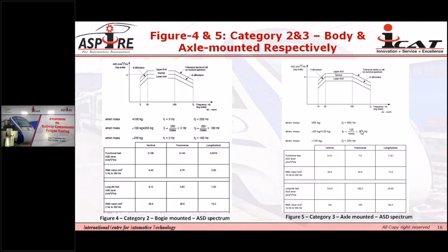And the important point, again, in this case, to calculate the lower and higher frequency, only the mass of the test sample will be taken into account to calculate the test frequency band, not the mass of the tester. So this table again defines the ASD level for the functional test as well as the ASD level for the long life testing at the increased vibration level. So this is all about the calculation of the frequency band for the different categories.